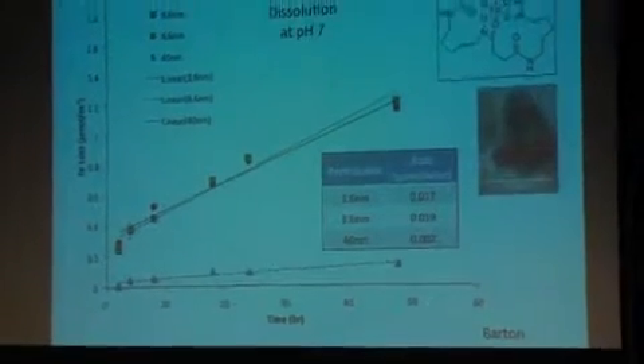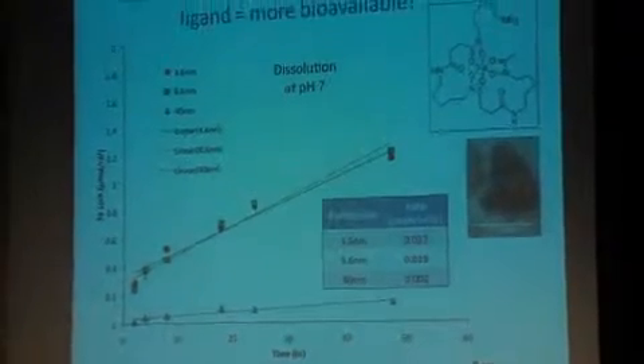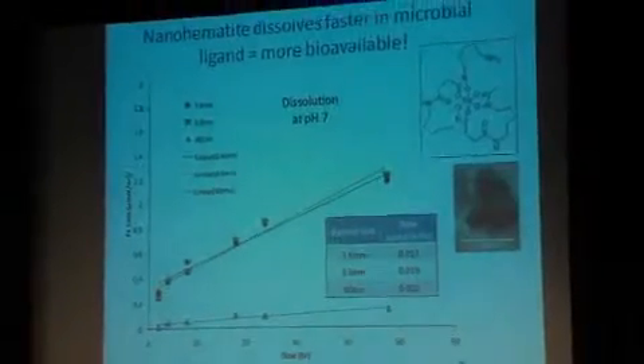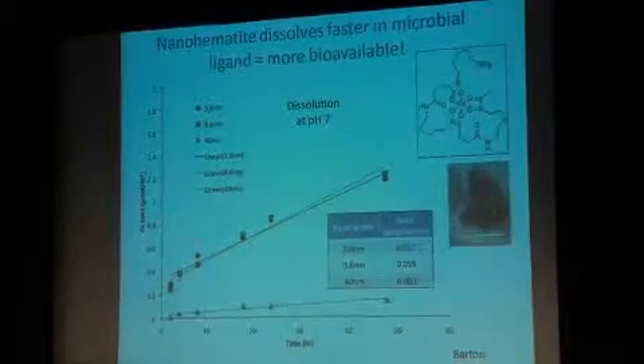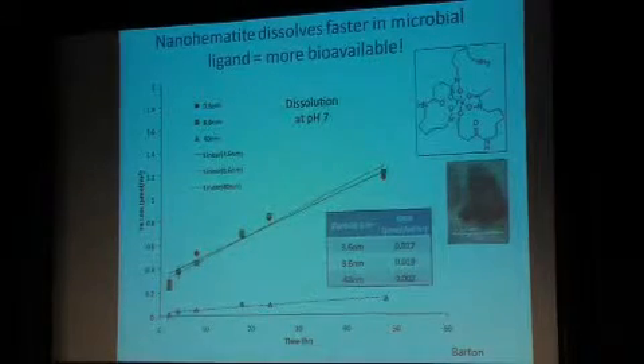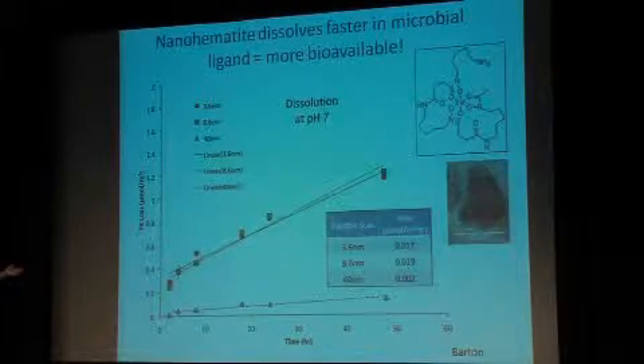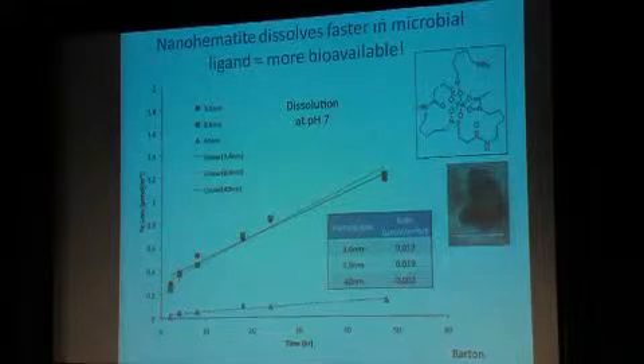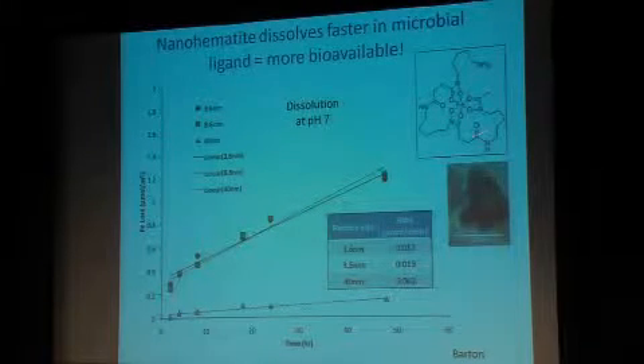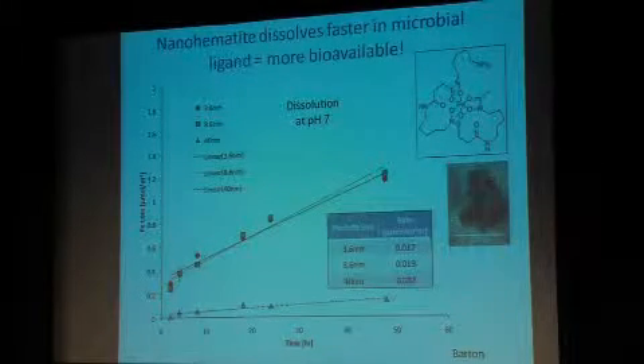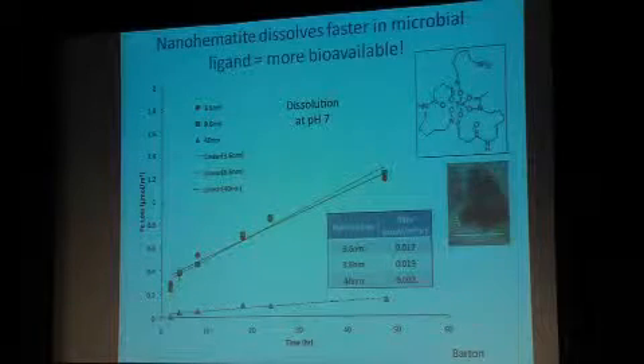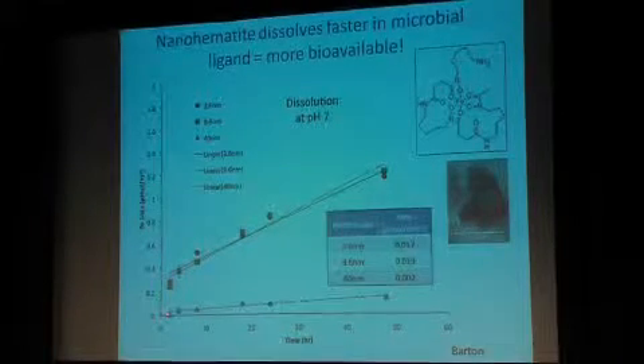And that's going to affect their reactivity. So here's one example of how this actually plays out in an experiment. Here we dissolved nanoparticles and larger particles, although you may not call all of them nanoparticles, of the iron oxide hematite in an organic ligand that dissolves the iron out of this. And here we have the time and the rate of iron removal.